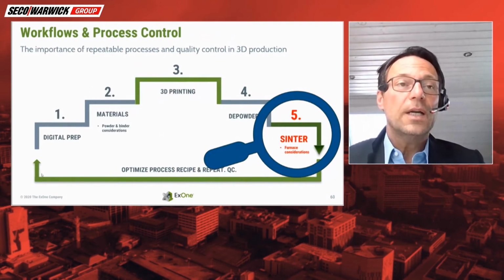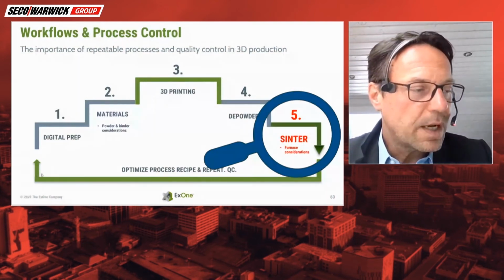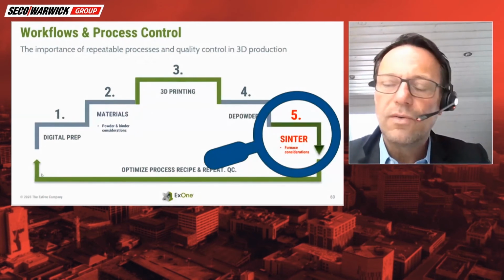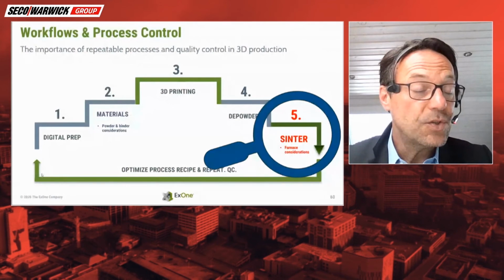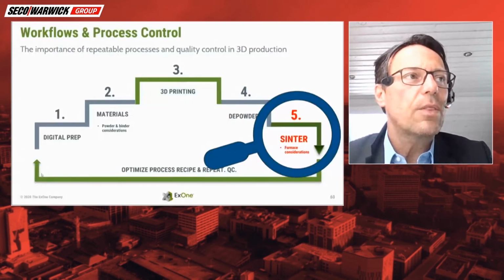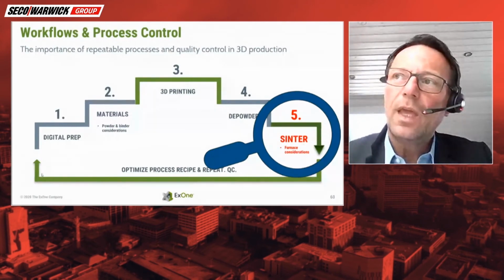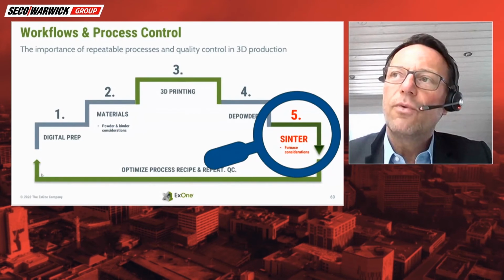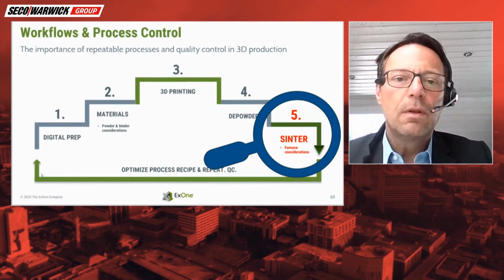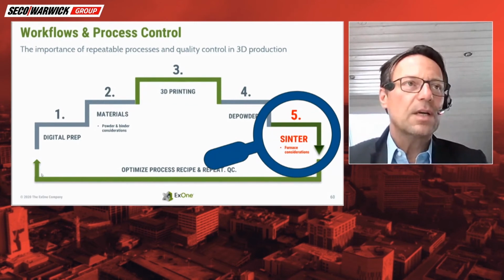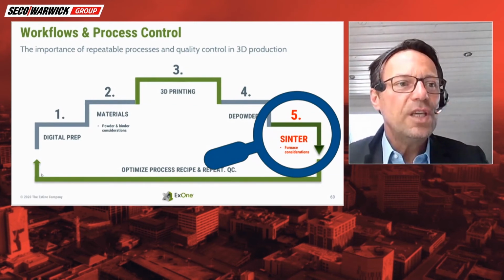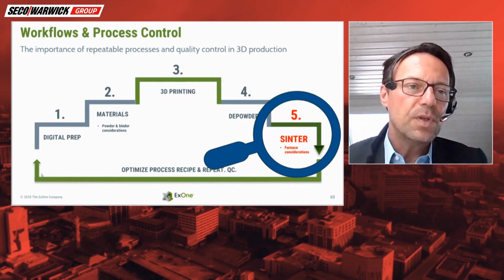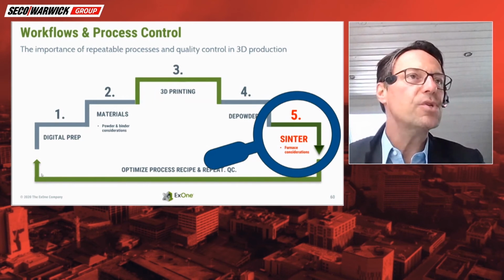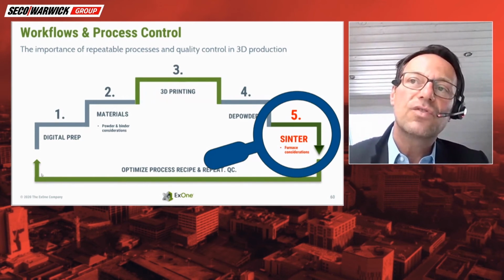Sintering. Of course, the furnace consideration is very important. I'll give you an example. If you choose to go for stainless steel, and in the early stages you want to start printing and sintering a 316, and the next day you think about maybe going for a 17-4. That sounds similar and very familiar, but if you want to achieve the best possible properties of a 316, you should go with hydrogen or high vacuum in the sinter process.